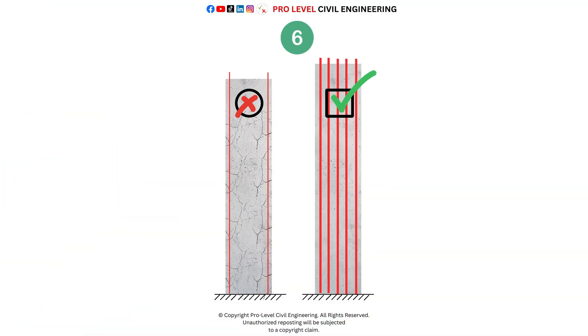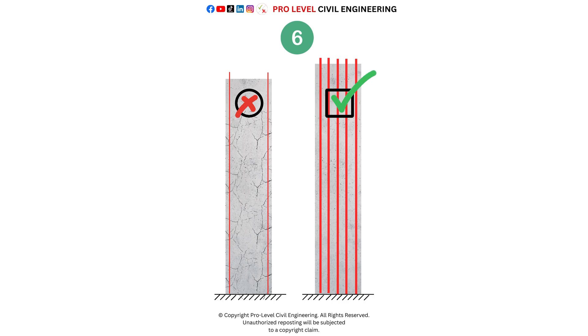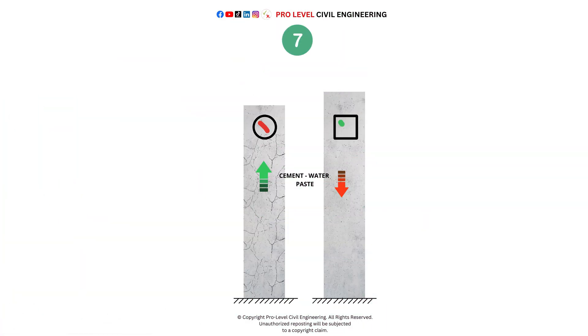6. Adding steel reinforcement to compression areas — when reinforcement steel bars are added to the compression zones of concrete, it significantly reduces the amount of creep. This is because steel has a very low tendency to creep, especially at the typical stress levels encountered in structural applications. In contrast, concrete deforms more over time under sustained loads, but steel remains much more stable.